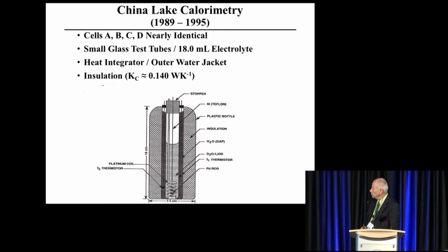The calorimetry I used, it took us a while to even break even. We're usually running negative, with less heat out than heat in, but finally we developed this calorimetry after about 4 or 5 months, and we used palladium we had at the lab in China Lake, and we did not get excess heat, and therefore China Lake and my name is in the ERAB DOE report, along with Caltech and MIT, as a group not getting excess power. And that's what we had for the first 6 months.